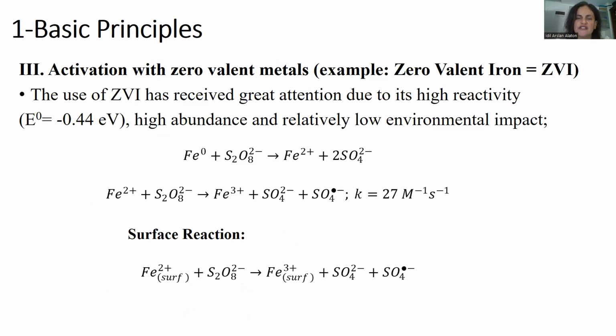So activation with zero-valent metals, that was also like 5 to 10 years ago. There was a lot of interest in zero-valent metals, using zero-valent iron and aluminium and also bimetals for activation of persulfates. Iron is preferred because of its high abundance, relatively low environmental impact. It's not a very toxic metal, and it has high reactivity. Here we have some surface and also bulk phase reactions. The zero-valent metal is oxidized by peroxydisulfate, and then the ferrous iron, since there's also ferric iron, undergoes a Fenton-like reaction. That's also possible in the bulk and on the surface of zero-valent iron.